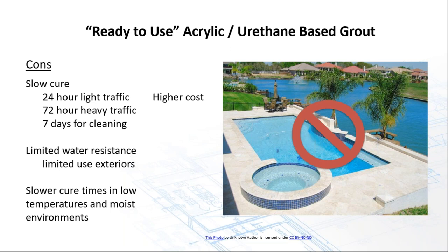Limited water resistant, limited use exteriors, slower cure times in low temperatures and moist environments. Now we state higher cost. Yes, it's a higher cost initially. However, if you take in consideration the labor cost on mixing bag to bag, letting the grout slake prior to installation, you're going to save on the labor. So again, it's initial cost, a little bit higher, but in the total package and the total installation, it's probably going to be a lower cost. So just keep that in mind, that that's not necessarily a factor versus a cementitious grout that you're going to mix.